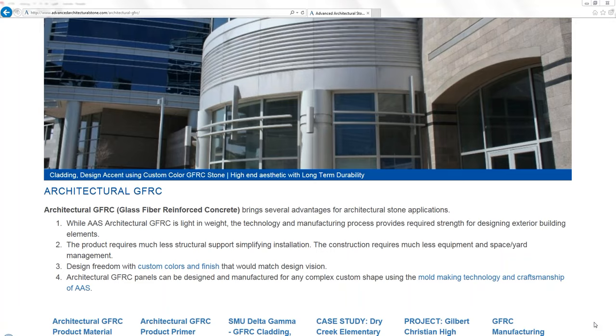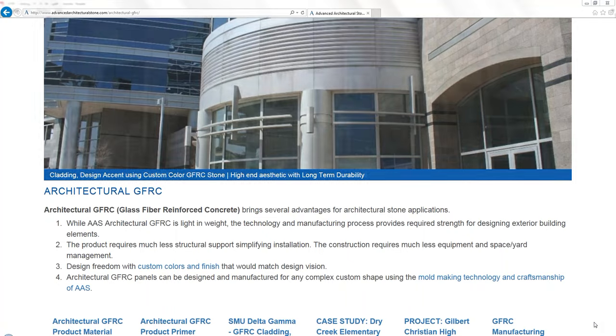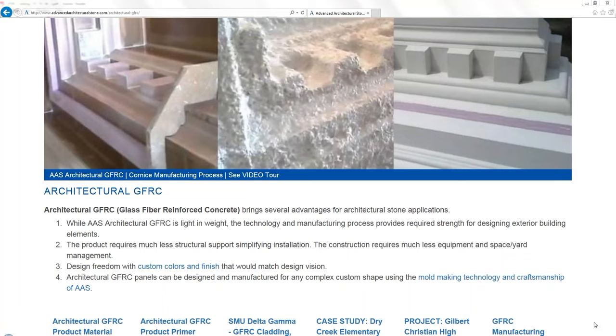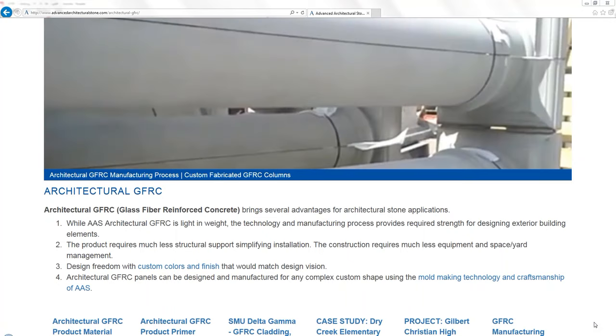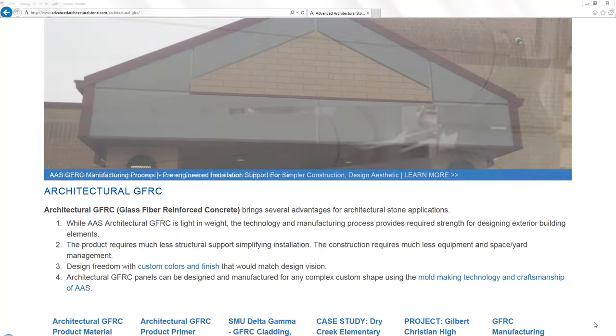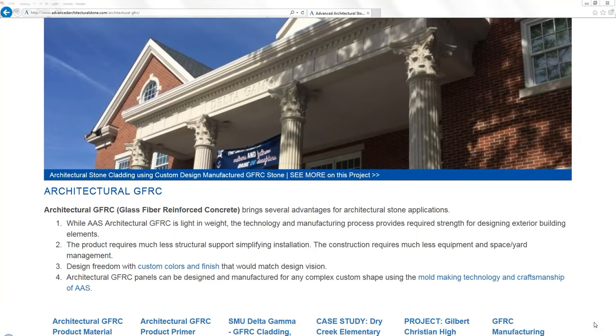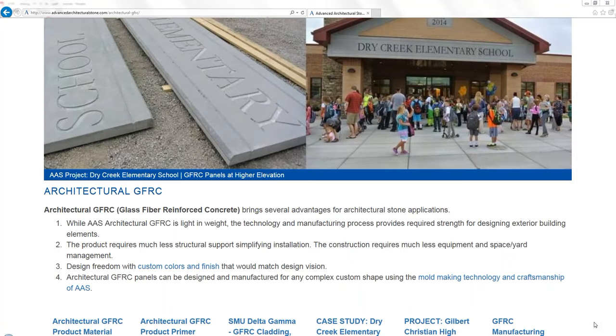We also will see in the details coming up that unless the product has a functionally strengthening shape, GFRC properties dictate the use of stiffeners on the panel or cornices. That would be a prefabricated plant-attached frame made out of cold rolled stud steel or structural tubes. It can be created with an upstanding skin formed rib on the back of the panel, or an integrally cast-in rib sprayed over foam, like expanded styrene foam strips. Each method reinforces and stiffens the GFRC skin, and also provides a means of connecting the panel to the supporting structure.